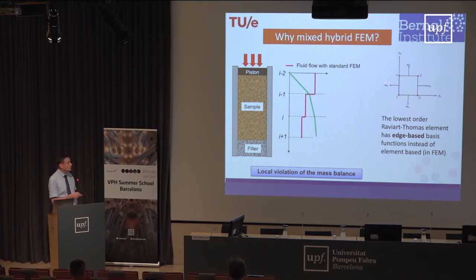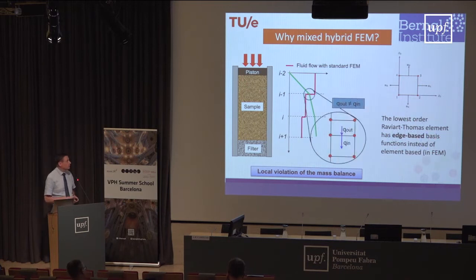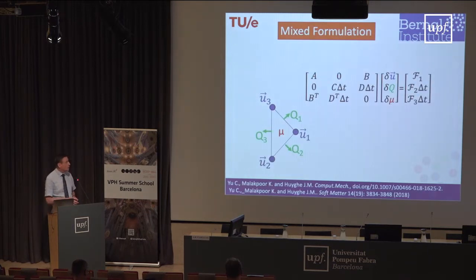You have in 2D, you simply have a square element with on the corners unknown displacement, and you account for the flux through each of the sides, edges, as degrees of freedom on top of the displacement. So where here we are using pressure, here we are using the fluxes across the edges. And we are going to use that element because this one will be able to force the fluxes from one element into the other element to be exactly the same. And that's what we do. And we force these two fluxes to be exactly the same. And the way we proceed is as follows.